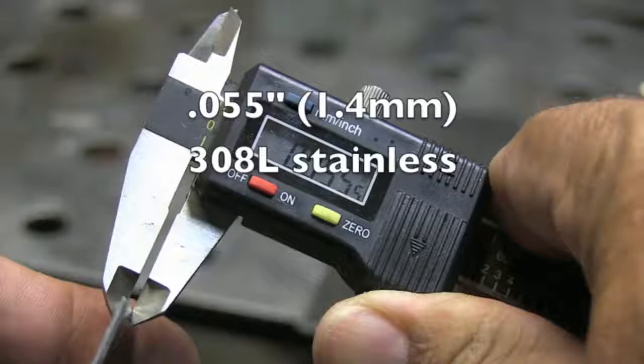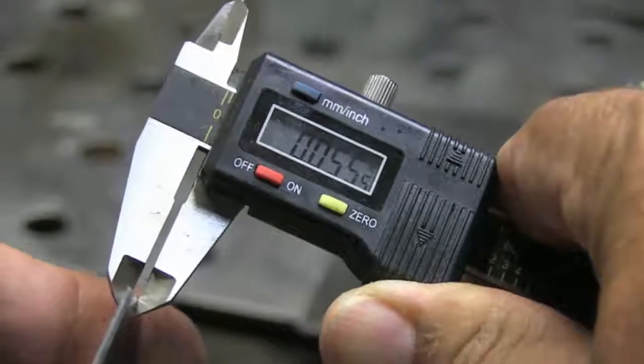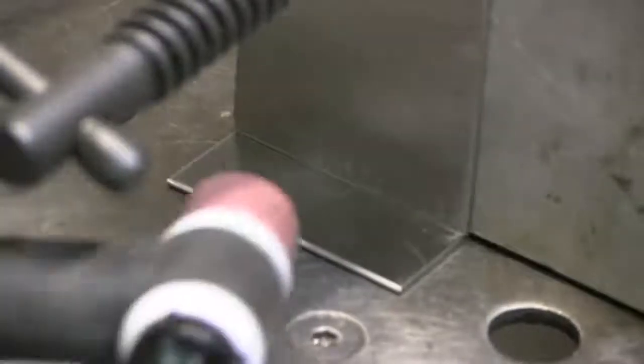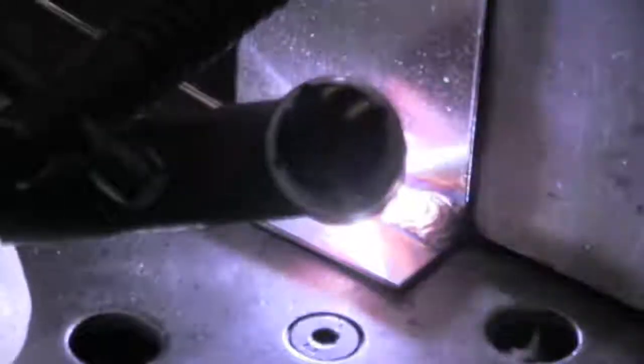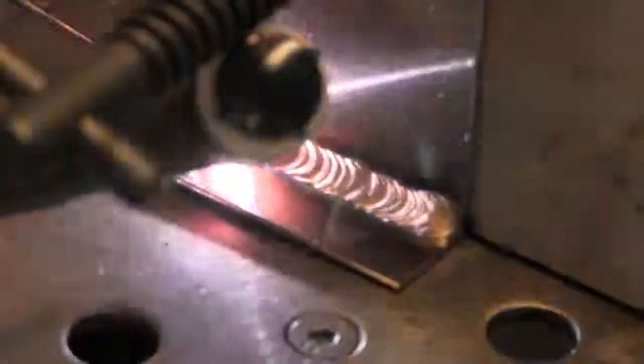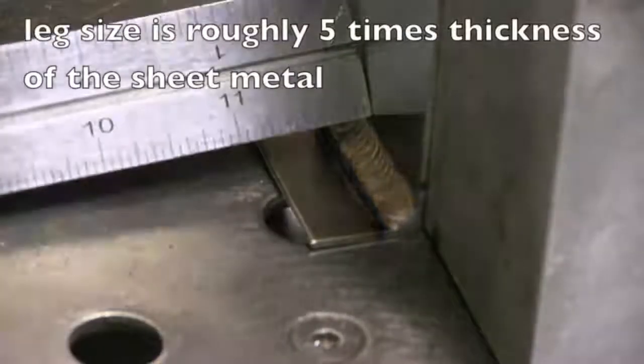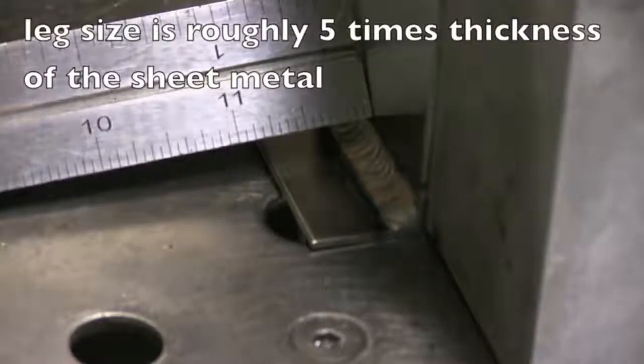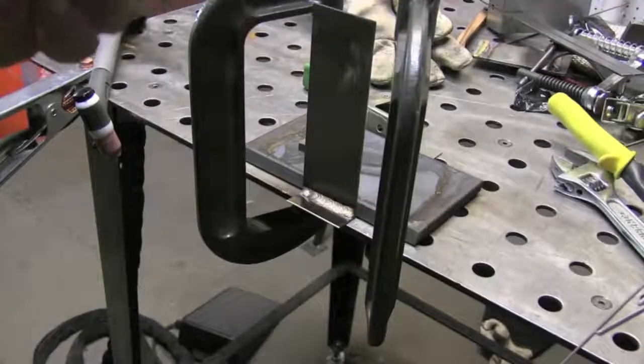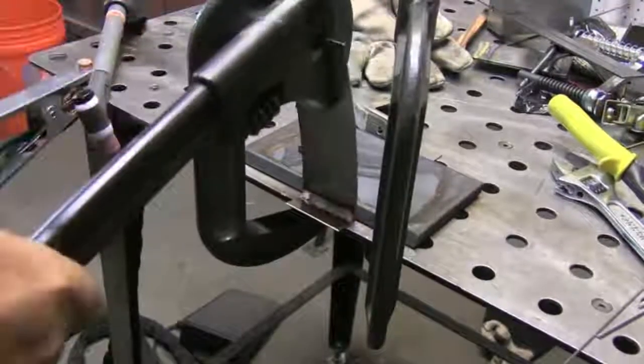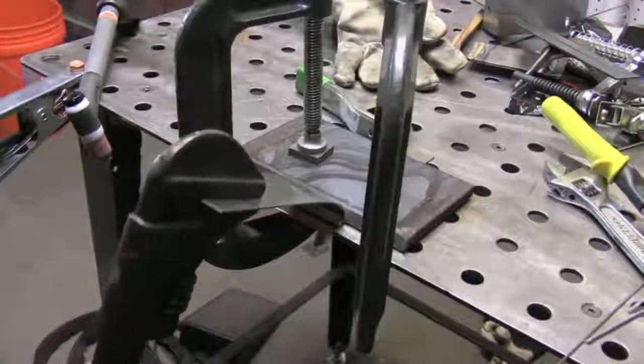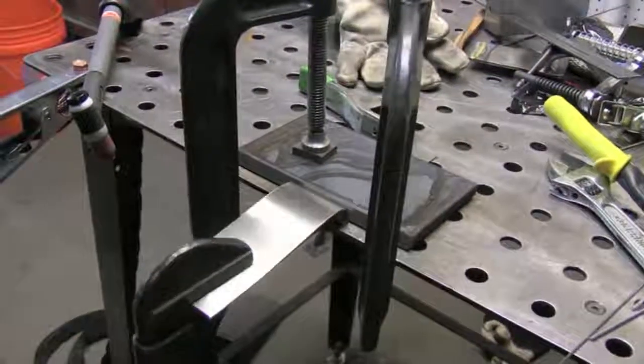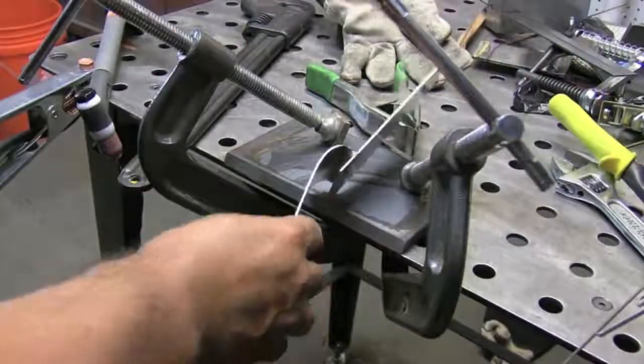If we take a look at some 055, some 1.4 millimeter 308 stainless sheet metal here, and we set up the same type joint with a very large fillet. I'm using large filler metal with a leg size roughly 5 times the thickness of the sheet metal. I put that in the same clamping arrangement here. It has no trouble, even on a one-sided joint there, holding back and bending and not failing.